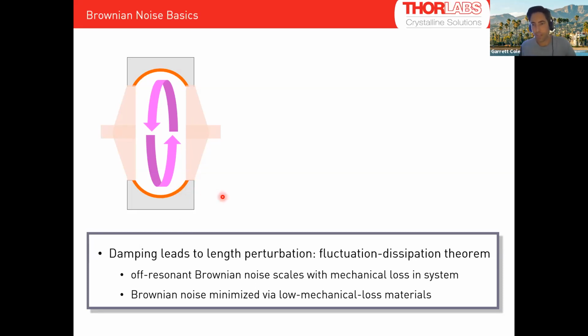Ideally, if this thing was at 0 Kelvin and very still, I would have a perfect frequency reference, right? Just limited by the line width of that thing. But in the real world, this thing is constantly moving. It's sitting at a finite temperature, so that spacer's expanding and contracting, the substrates are moving, even if it's ULE, right? Even if it has zero expansion, even if I do the best job I can to hold the temperature to exactly the temperature I want, there are intrinsic thermal fluctuations that we can't get rid of. So it is this intrinsic Brownian motion that drives the length instability of that cavity.